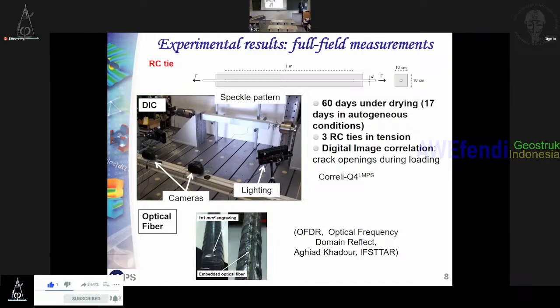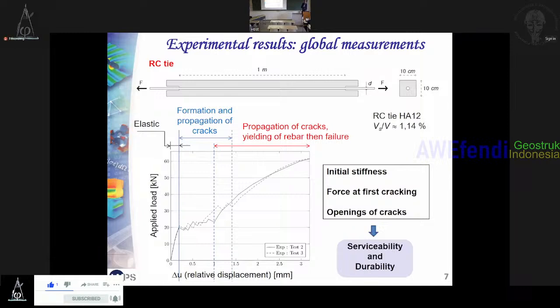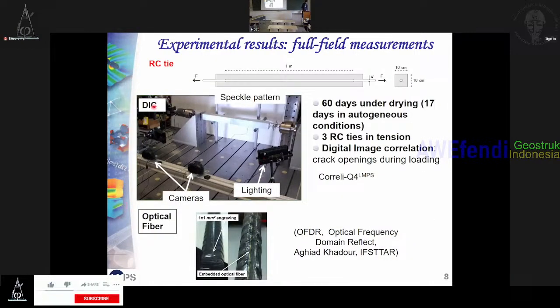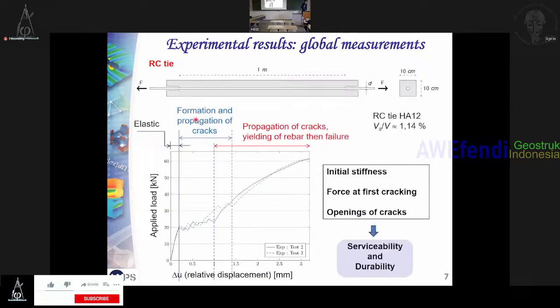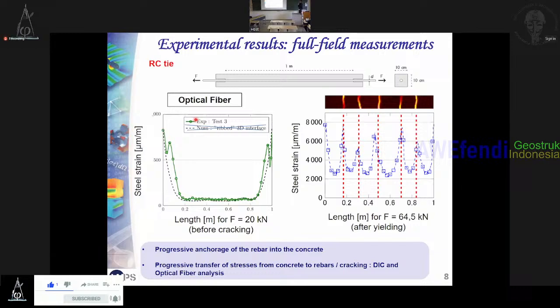But I did a similar test, and once the crack is formed on one side, it tries to bend. Then the rigid frame also affected the crack. I agree with you. It will also depend on the boundary condition. Here we have a device to allow rotation of the sample. You can see the cracking pattern is not completely vertical, but it's quite nice. Perhaps this is not because of the rotation of the sample, but just because of the heterogeneity of the material. Okay, I got it. Thank you very much.